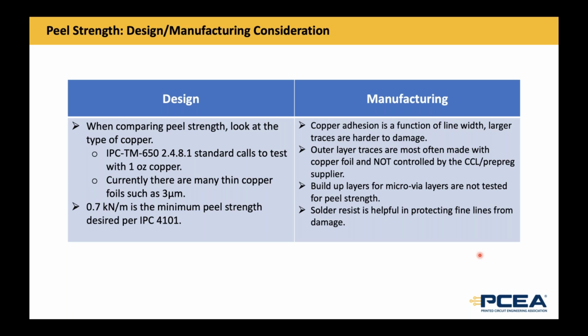The buildup layers are not tested for peel strength by the supplier of the material, because that material is generally not used as is, and you can only test it once you've made it into a structure. I think it's interesting that most people don't understand that microvia layers that use, say, an MSAP process to define them, the peel strength can't be measured.